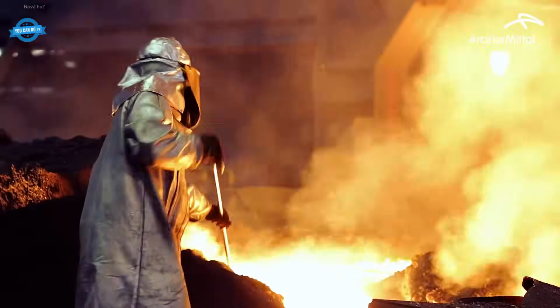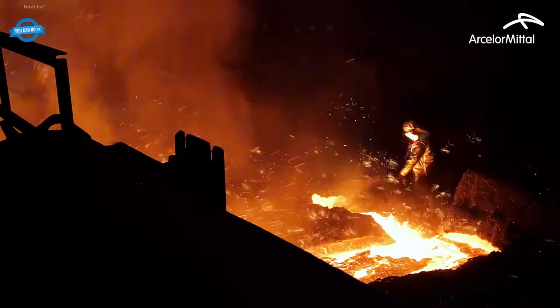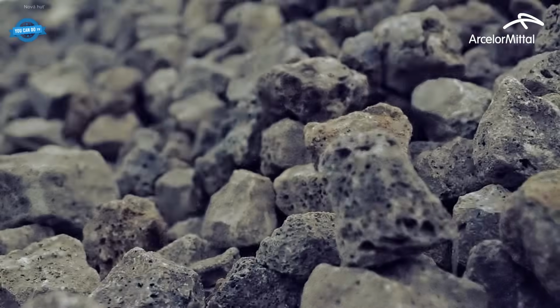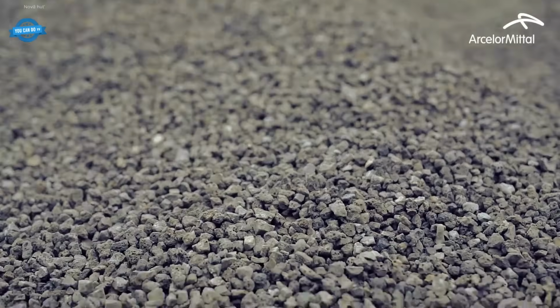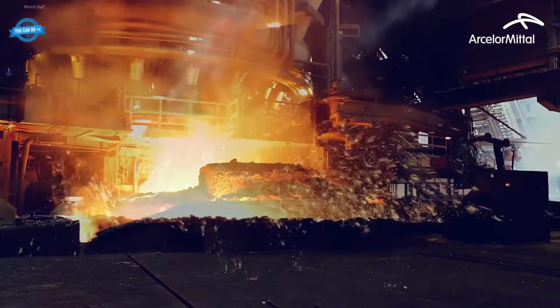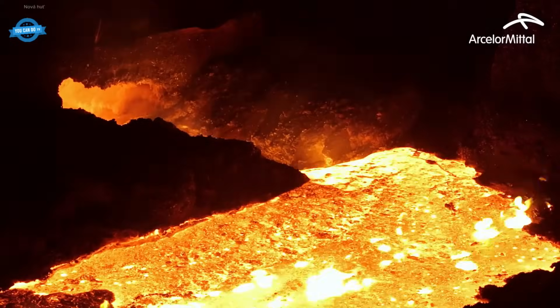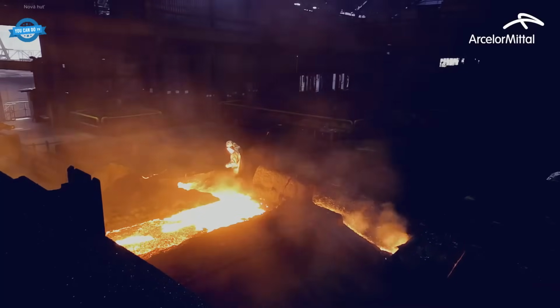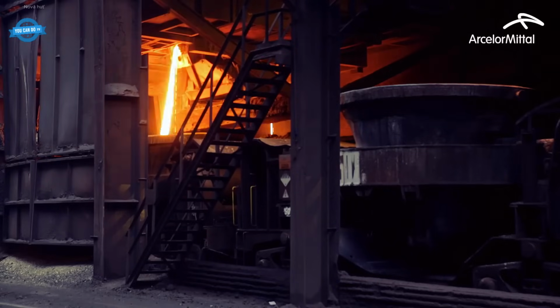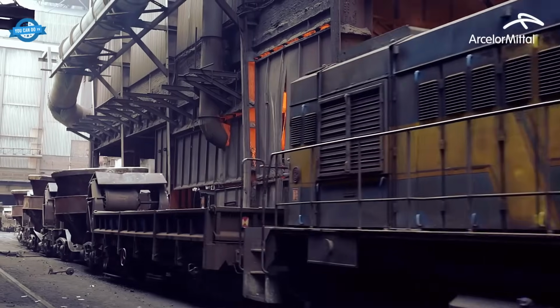Molten blast furnace slag is collected from the bottom of the furnace and transferred through a trough into a slag granulation tank. The slag is then transported away for cooling. Workers pour the slag in the tank into a trough and use high-pressure water jets to rapidly cool the slag, causing it to vitrify into a glass bead material. The resulting mixture of water and granulated slag flows into a settling tank, where the slag is separated from the water. After dewatering, the slag is transported by truck to the processing site.